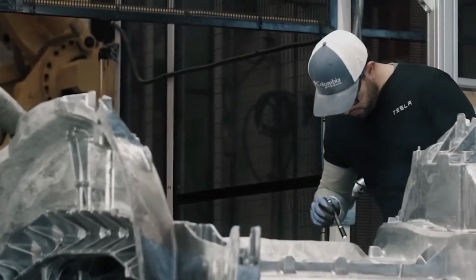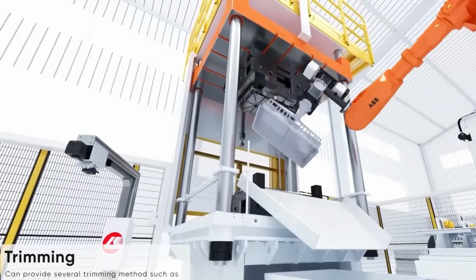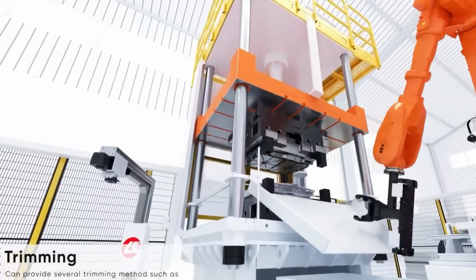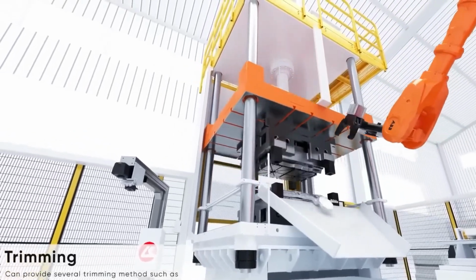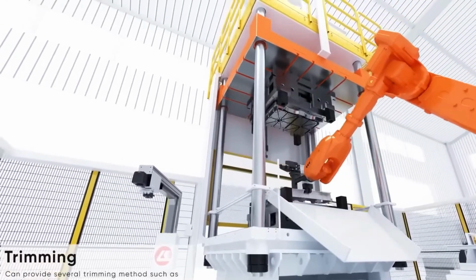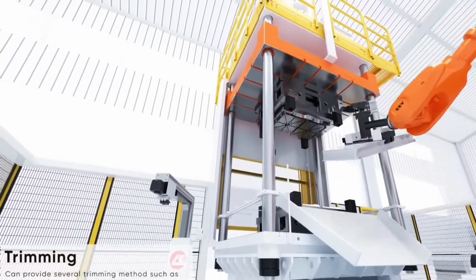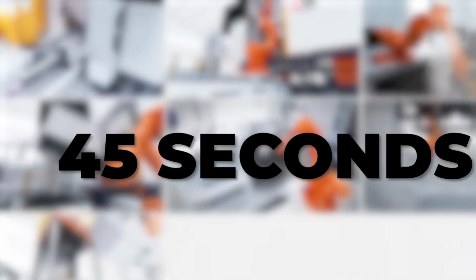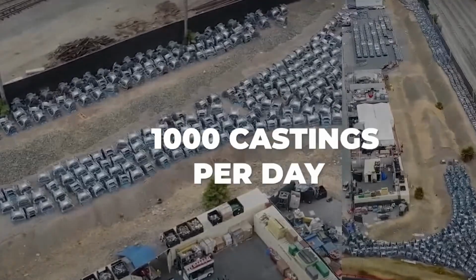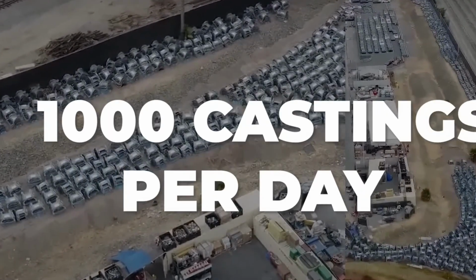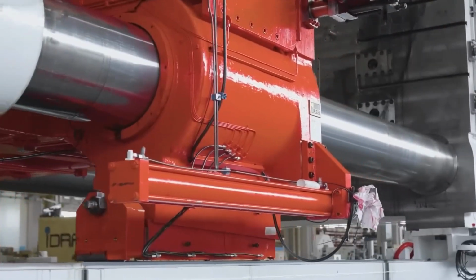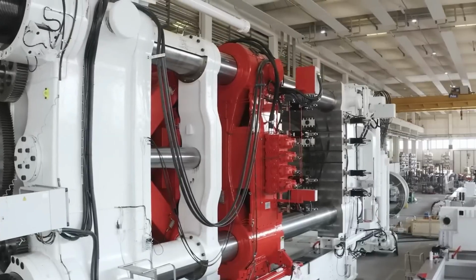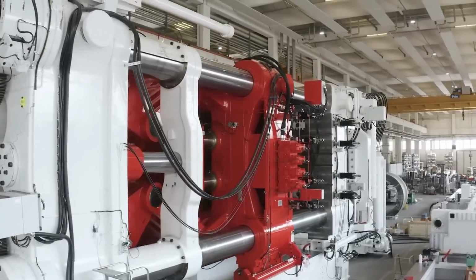The die mold is prepared with a thin coating of soybean oil, just like greasing your baking pan, and then a vacuum is used to remove air from inside the mold. The metal is pumped in with a high-speed plunger like a syringe needle, and the casting is formed. This action takes less than 1 second to complete. The clamp releases the two halves of the mold, and a robot picks up the casted section, which is now cooled to 750 degrees Fahrenheit. Then the part goes into a water bath to bring it down to a reasonable temperature.